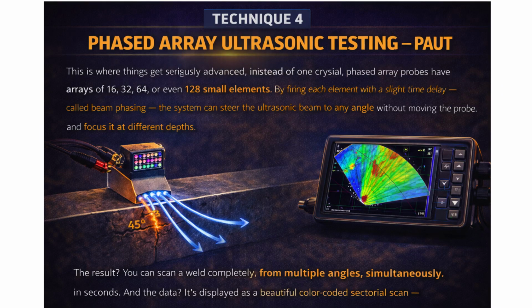Phased array ultrasonic testing, PAUT. This is where things get seriously advanced. Instead of one crystal, phased array probes have arrays of 16, 32, 64, or even 128 small elements. By firing each element with a slight time delay, called beam phasing, the system can steer the ultrasonic beam to any angle without moving the probe, and focus it at different depths. The result? You can scan a weld completely, from multiple angles, simultaneously, in seconds. And the data? It's displayed as a beautiful color-coded sectorial scan, like a radar sweep, showing you exactly where defects are and how big they are.